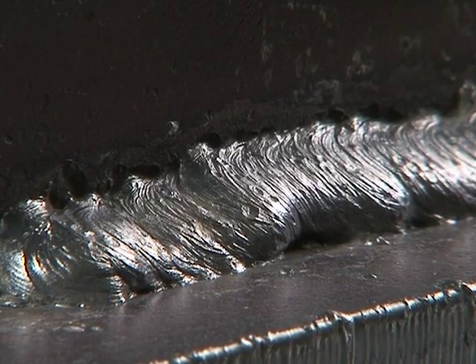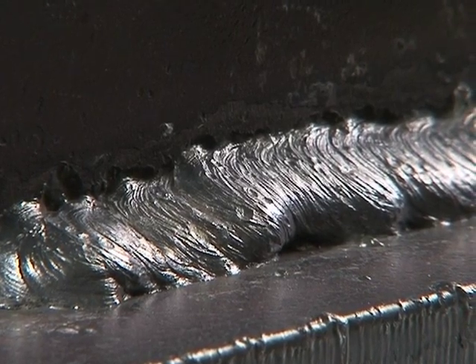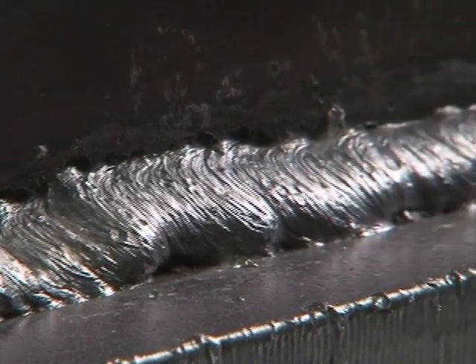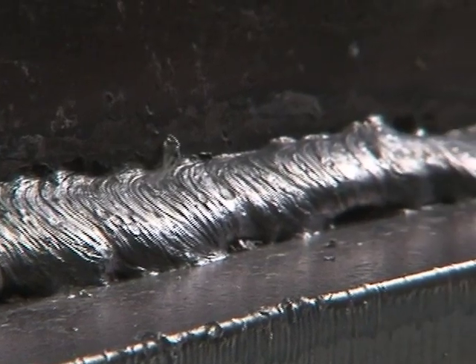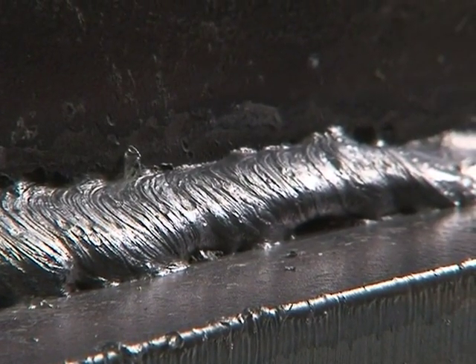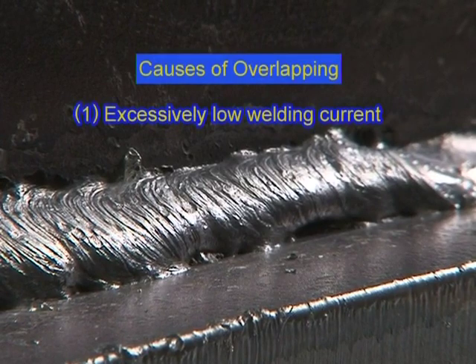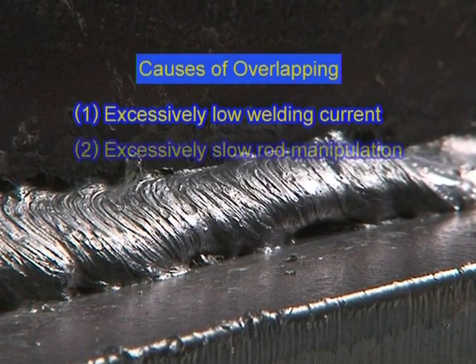Overlapping is a defect frequently encountered on the horizontal plate side during horizontal fillet welding. Overlapping means that the deposited metal has not fused with the base metal, but merely lies on top of it. Causes include excessively low welding current and slow rod manipulation.